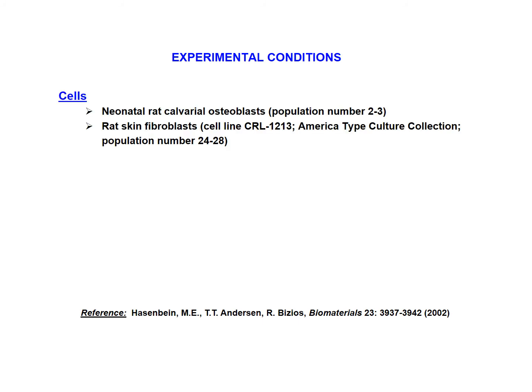The experimental conditions for Meredith's experiments are summarized on this slide. First and foremost, neonatal rat calvaria osteoblasts, the bone-forming cells, were used, and one more additional detail for this study was the use, in parallel but different experiments, of rat skin fibroblasts as a comparison line for the functions of osteoblasts versus those of fibroblasts.